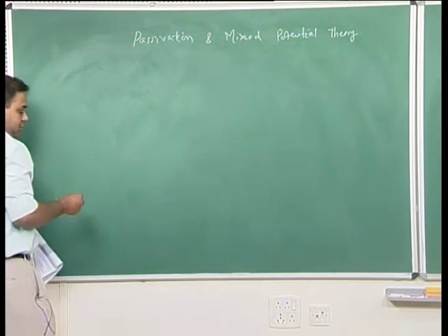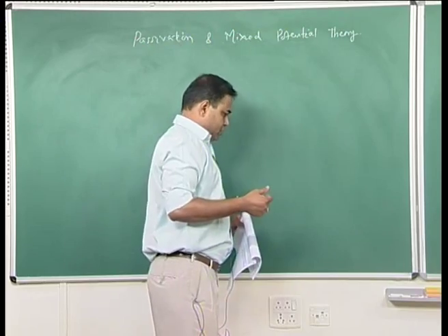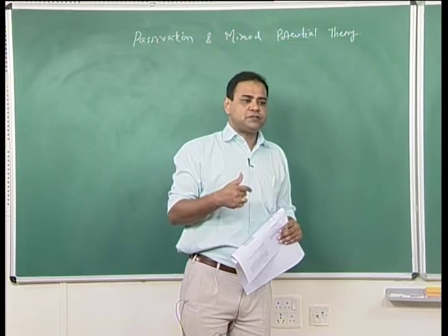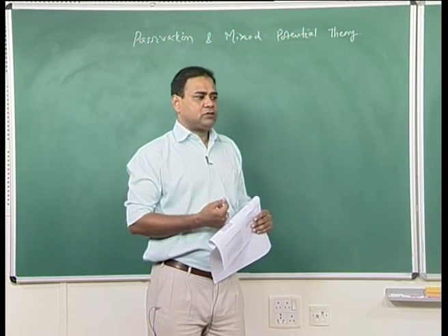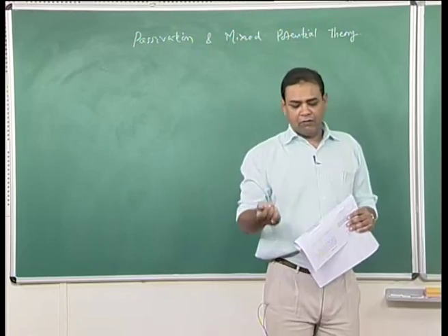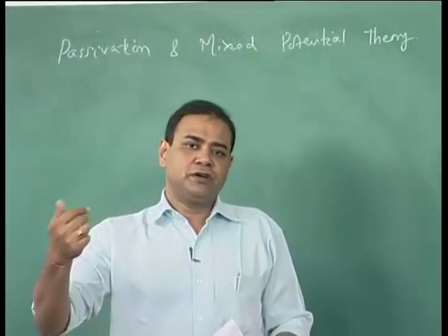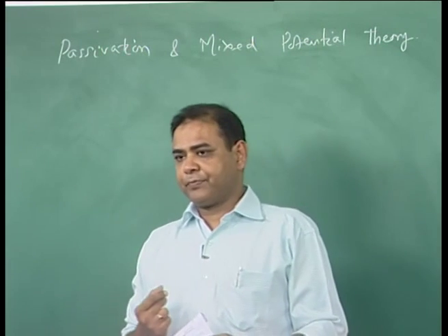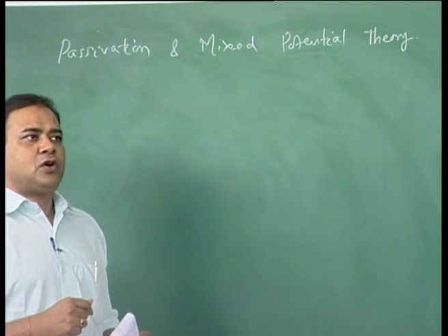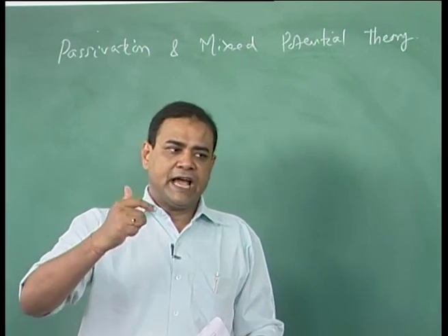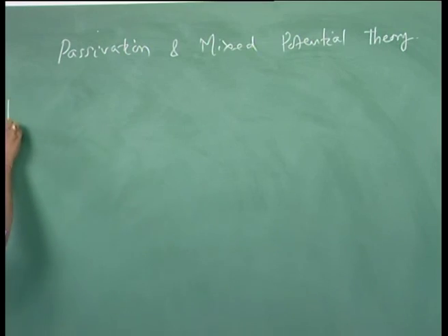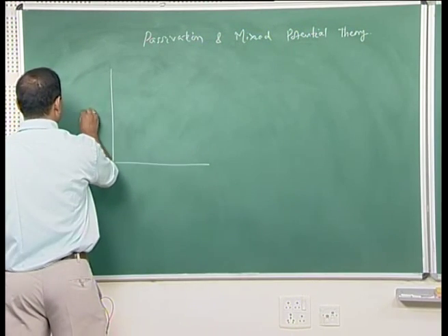Now, we have seen that when you have a cathodic reaction along with the anodic reaction, and the metal which is showing anodic reaction or the dissolution reaction, that cathodic reaction actually takes the potential of the metal which is basically dissolving to a potential depending on the cathodic reaction, either to active region or to a passive region, or it can be in the unstable passivation region.